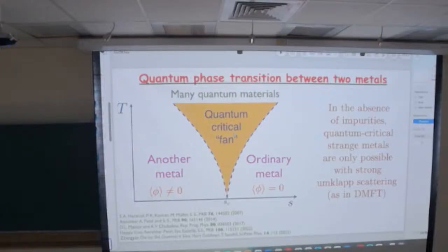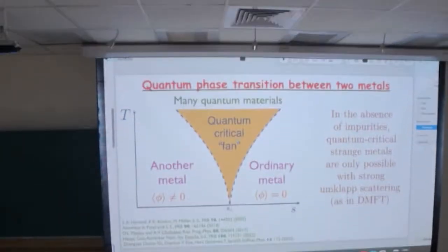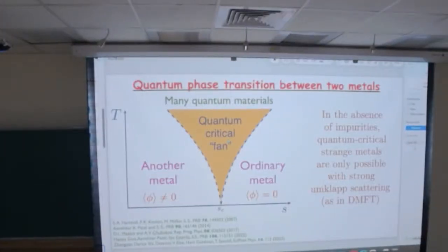So is this phi connected to the hydrodynamic behavior in any parameter of hydrodynamicity? Well, it leads to this conserved momentum in this theory, yeah. However, in the real world, this theory doesn't work at all. Unlike in graphene, where the hydrodynamic theory works, here the hydrodynamic theory fails. It doesn't give you linear T resistivity, period. In graphene, you get a resistivity over e squared h because of particle hole symmetry. Here, there's no particle hole symmetry, so in fact it gives you zero resistance.